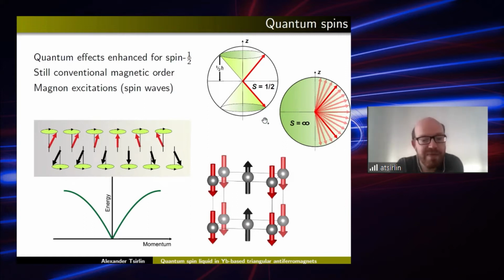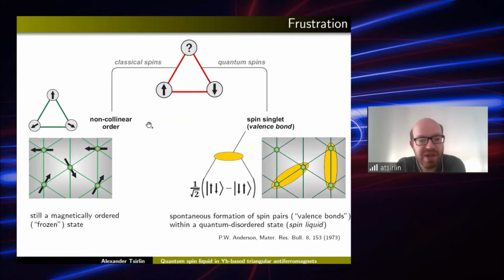I need spin 1/2. But this is actually not enough, because if I just take a spin 1/2 atom and construct an antiferromagnet out of the spin 1/2 atoms, then it will be still magnetically ordered, and the excitation will be pretty much the standard magnet. So that won't be a spin liquid yet. We need the second ingredient, and the second ingredient is the frustration, the effect of competing exchange couplings, for example, on a triangle.